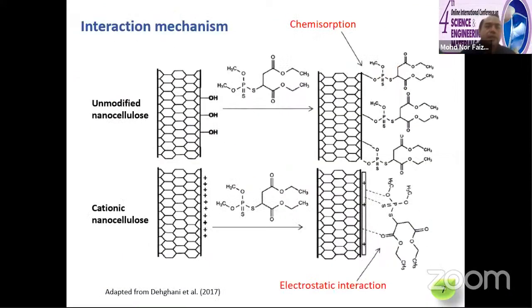So this slide shows the interaction mechanism between the nanocellulose and the organophosphorus compound. I divide it into two, the unmodified and modified nanocellulose. For unmodified nanocellulose, the presence of the hydroxyl group can form chemical adsorption with organophosphorus. The alkyl and hydroxyl groups will get connected by producing water. We can also modify the nanocellulose by making it positively charged, known as cationic nanocellulose. So it has a positive charge here.